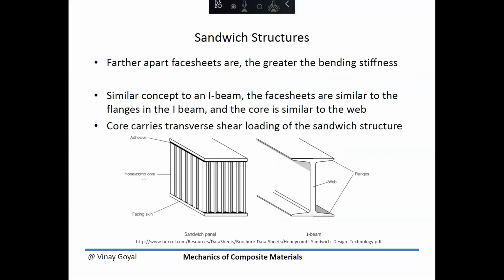So what we've really done is we've actually constructed almost like an I-beam. That's what you do with the I-beam. You put the flanges as far apart as possible and put very minimal material in between, which we call web. The farther apart the face sheets are, the greater the bending stiffness. And that concept is very similar for an I-beam. You can see that this empty area here basically reduces the average modulus between these flanges. That's what this sandwich structure is doing. Both of these are improving the bending resistance by quite a bit. The core carries typically the transverse shear loading, so this core is doing the work for that, while the face sheets take the in-plane loads or the bending loads as well.